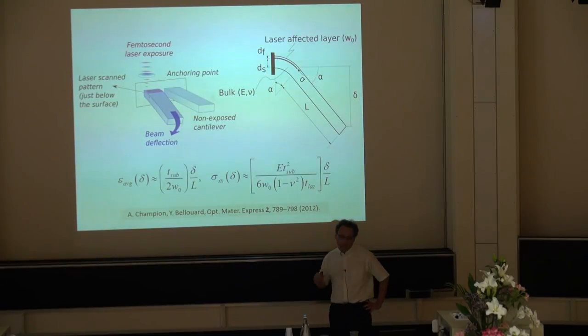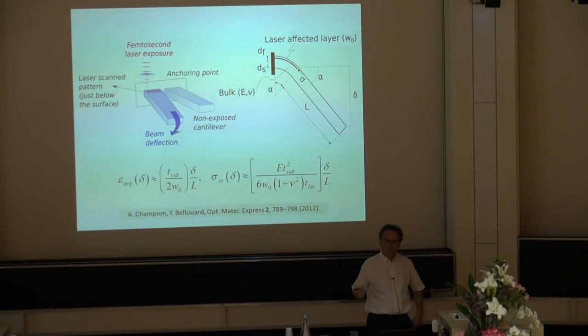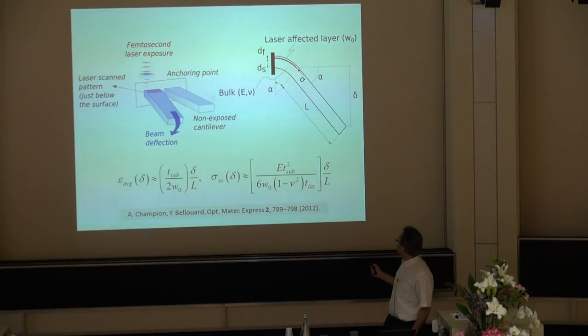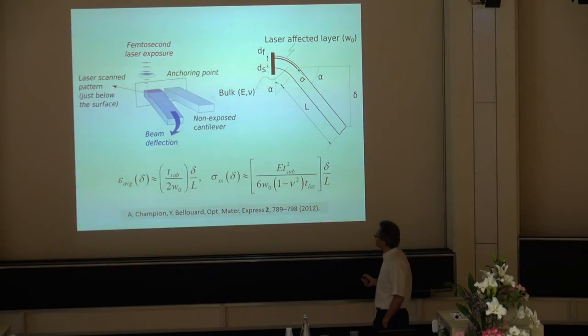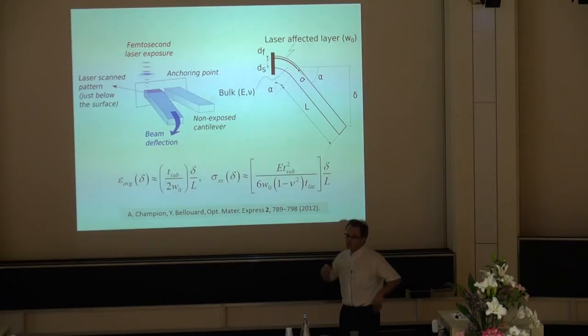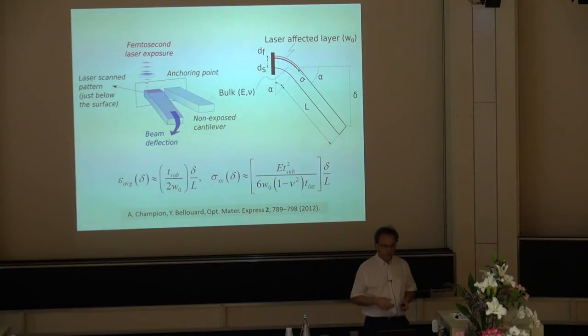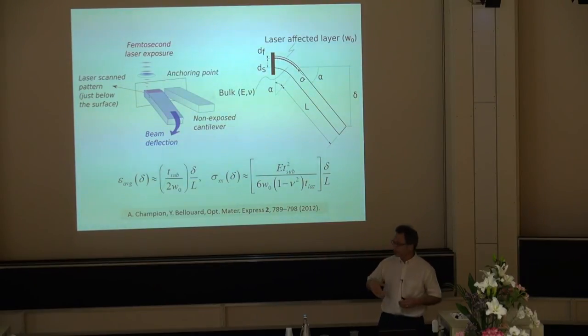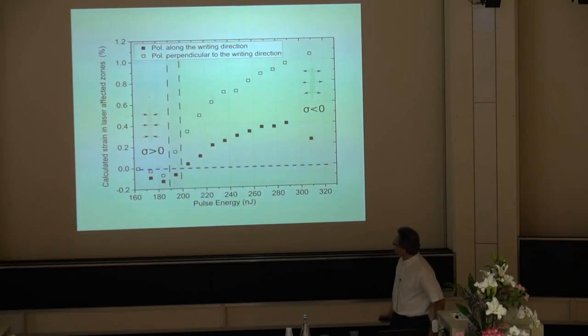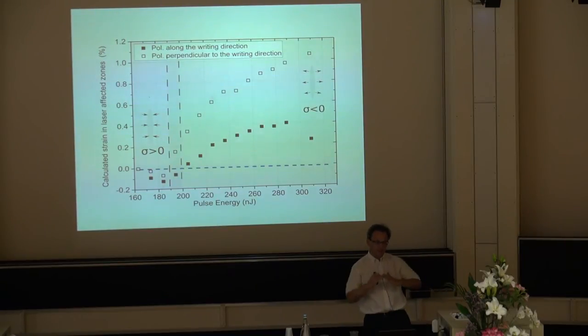I'm just showing you an example here, which are cantilever beams. If you re-expose to the laser beam afterwards, you can investigate how much this volume has changed, how much it has expanded, just by measuring how much your cantilever is moving. If I expand a lot, then it will move down. If I shrink, it will move up. So that's telling you something about the volume changes due to the laser. And it's very intriguing that when you change the pulse energy, first you shrink the material and then it expands.